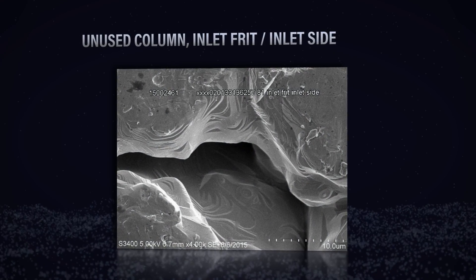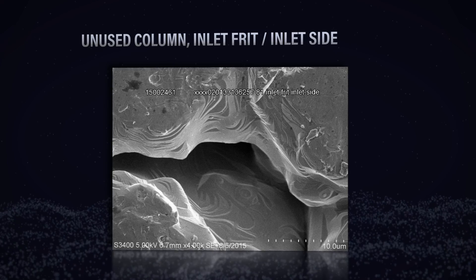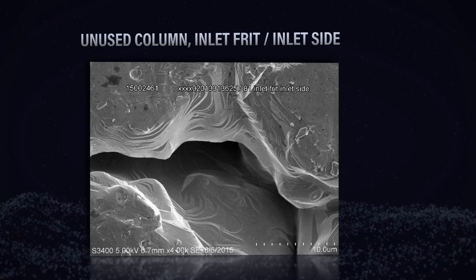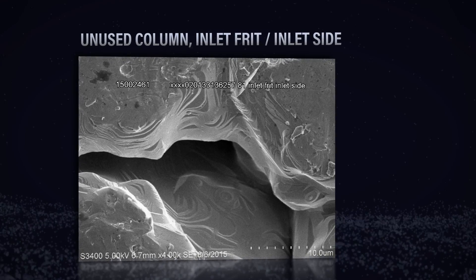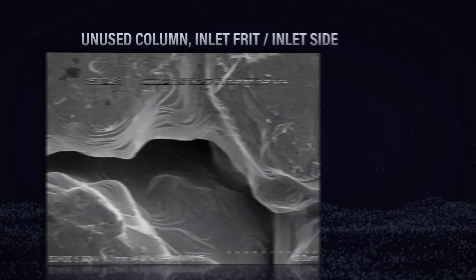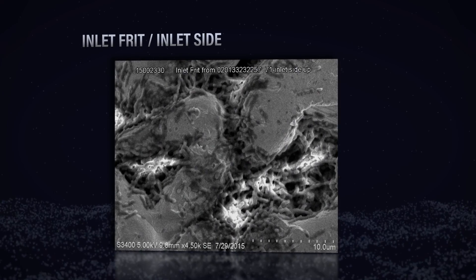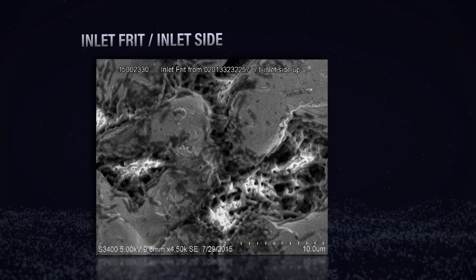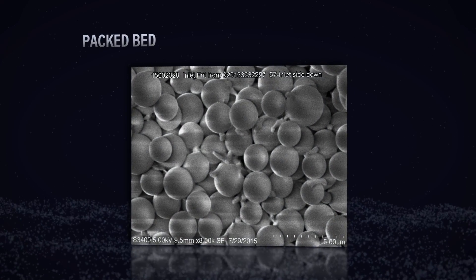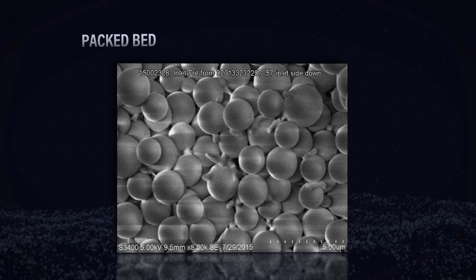You never want to advocate pulling a column apart for any reason, but let's take a look at some of the images from the SEM. So if we look at this first image, we can see the frit looks exactly the way it should — nice and clean, the way a column should look if you're using clean mobile phases and taking care of your system. This was for an unused column, so it's pretty much the way it came out of manufacturing. Now let's take a look at the next SEM image. That's terrible — we're seeing a lot of bacteria. You can see it interlaced in between all the frit material, it's everywhere. And you can even see it on this next image into the packed bed itself, in and around the particles, really fouling up the column.